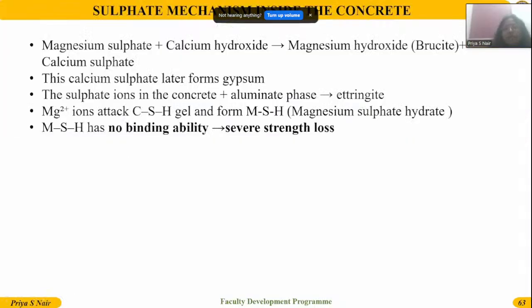Then the resistance to sulfate attack. Here we used magnesium sulfate, mixed in water, and we placed the samples inside for different durations. We used wetting and drying, 14 days wetting and 40 days drying, with 4% magnesium sulfate. When magnesium sulfate reacts with calcium hydroxide, magnesium hydroxide, that is brucite, is formed plus calcium sulfate. This calcium sulfate later converts to form gypsum.